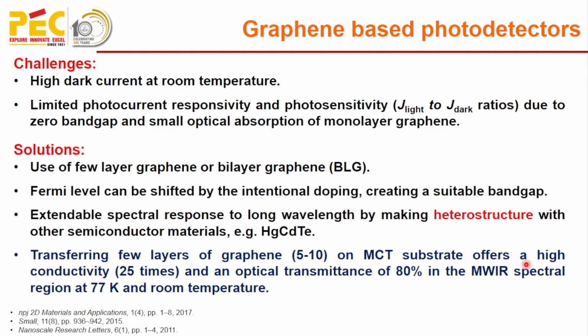And practically it was found that transferring a few layers of graphene onto a mercury cadmium telluride substrate will give high conductivity and high optical transmittance of 80% in the mid wavelength region at 77 Kelvin and room temperature.